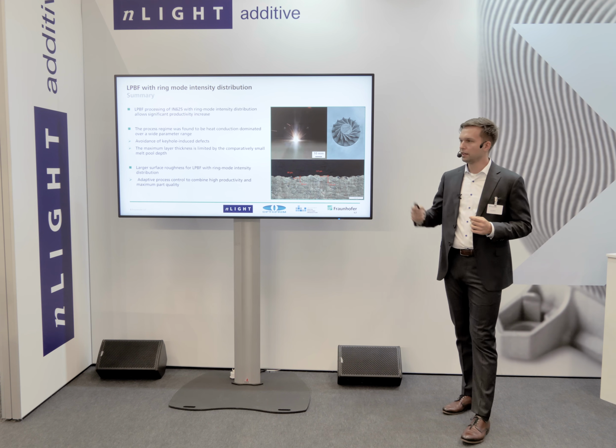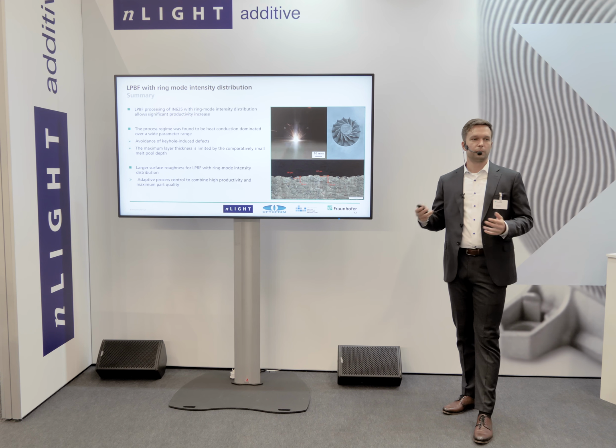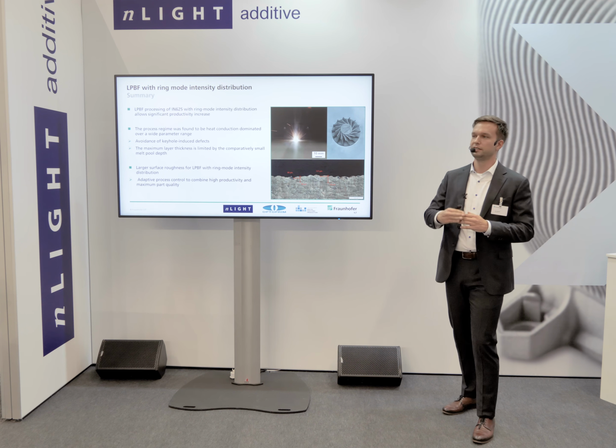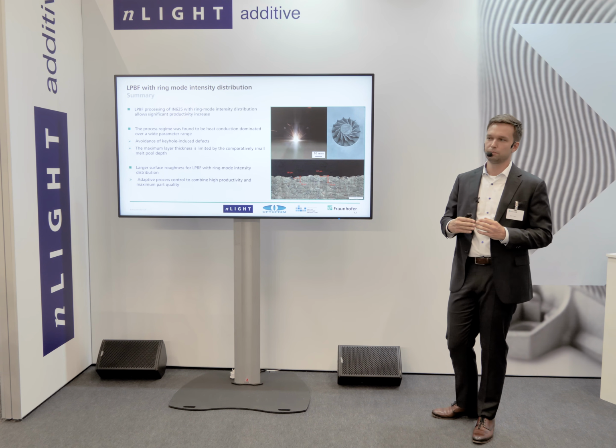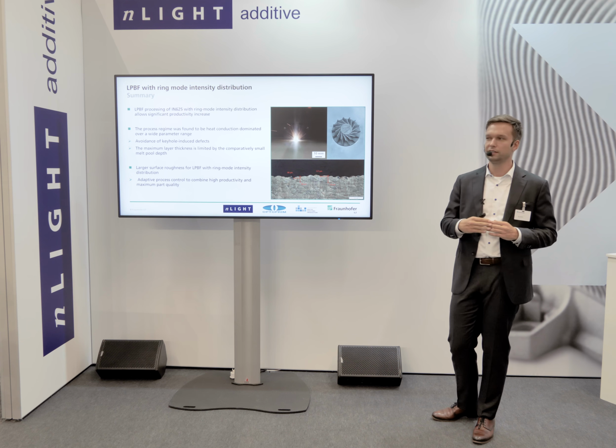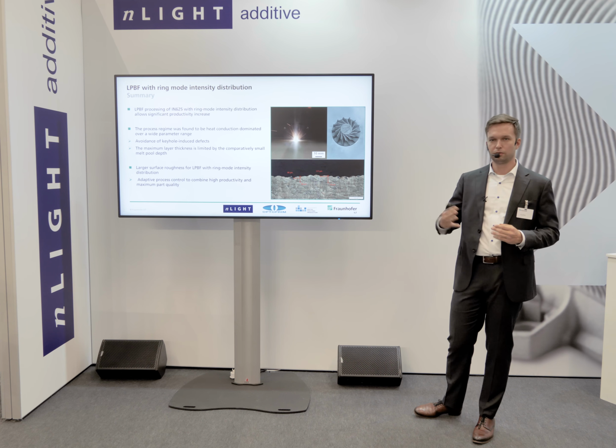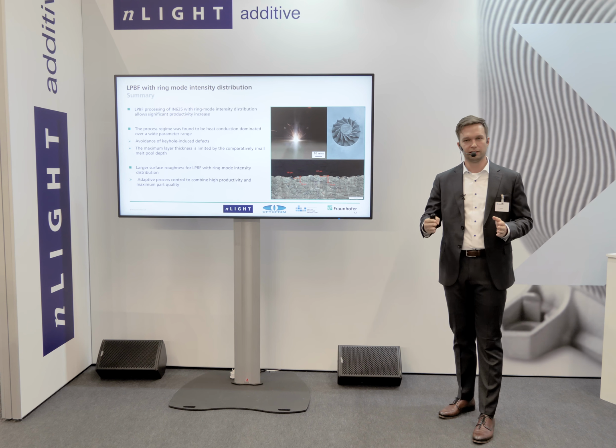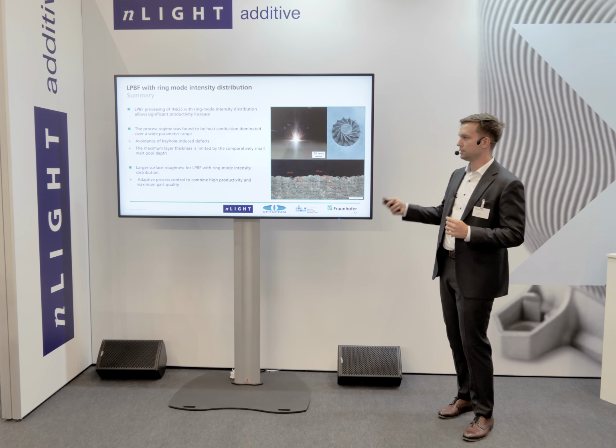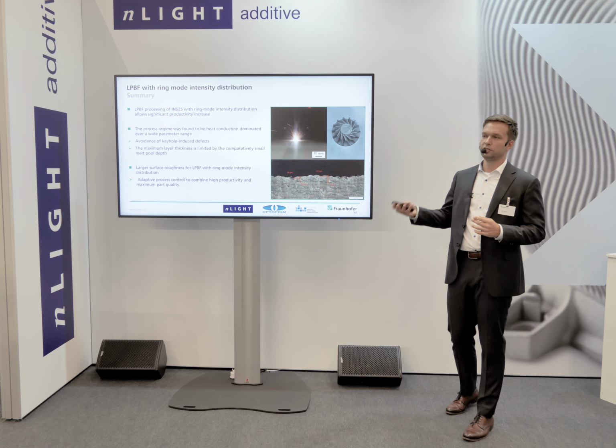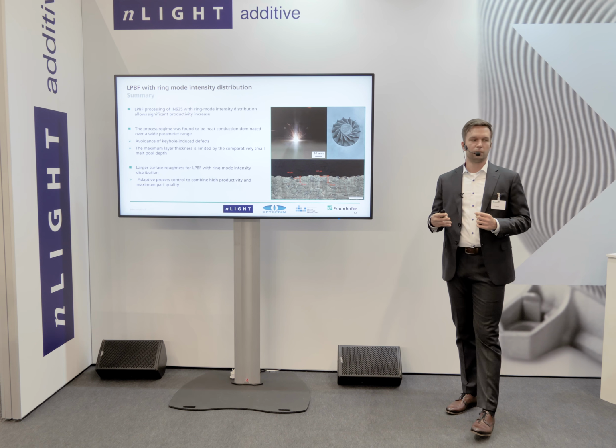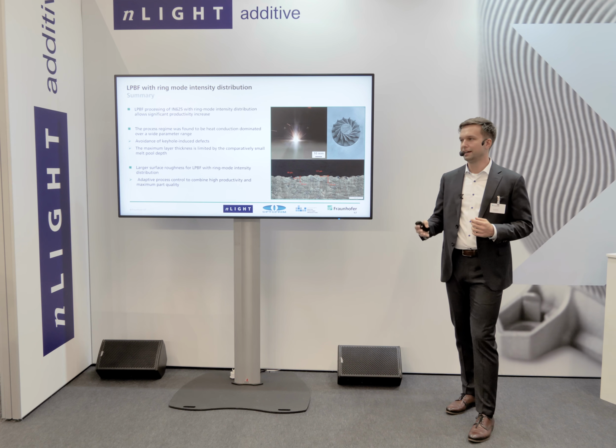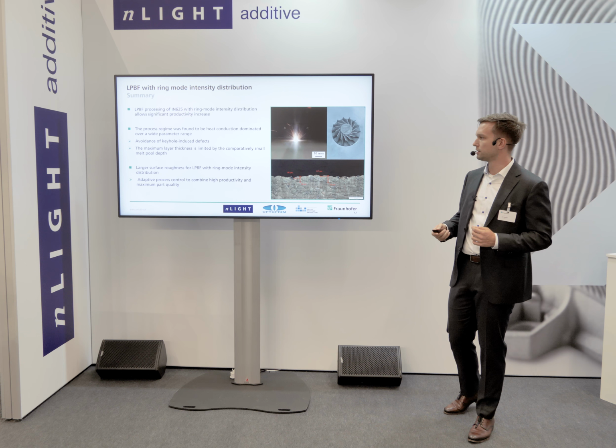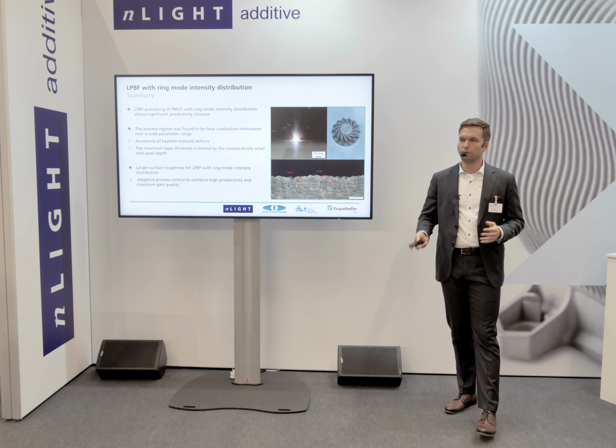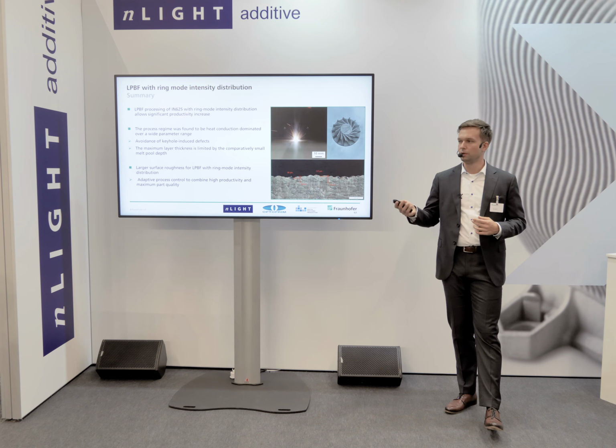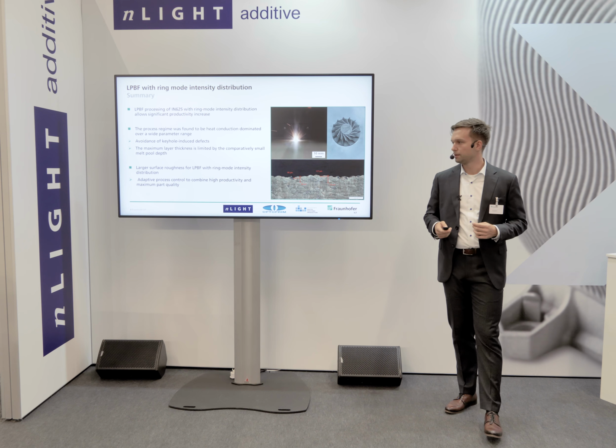Nevertheless, there are also some constraints when it comes to layer thickness. It is difficult just with this heat conduction based process to really scale the productivity. You have rather to scale via the hatching distance and the scan speed. Also, the contour when just processing with the ring mode beam is slightly rougher than for the Gaussian reference, which can be solved by combined adaptive processing with the switchable AFX laser beam source.